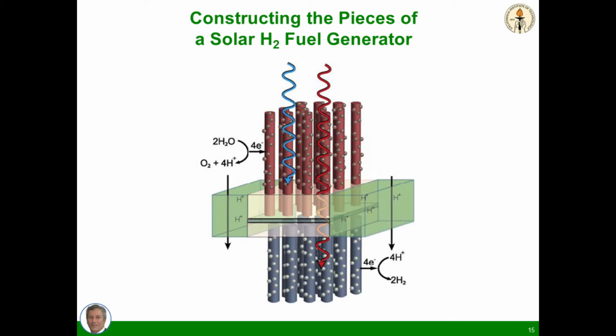And you can see that this microrod array has an internal sponge volume that lets the protons go down the shortest distance possible from where they are made to where they are consumed. And this is critical to avoid deleterious resistance losses, because the protons in water are less mobile than the electrons in solids, and they're the slow step that drags the system down otherwise. So that's our blueprint as to how we're going to build a 747 instead of building this birds-with-feathers architecture to get this thing to fly.